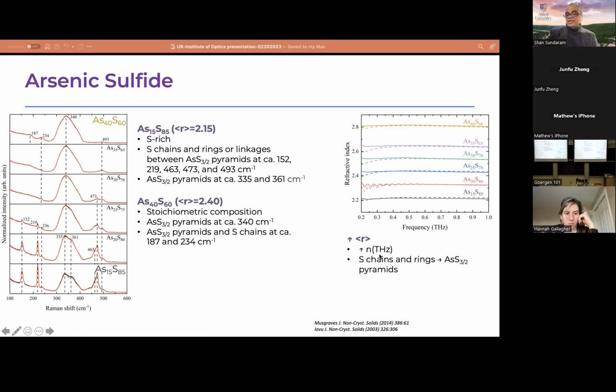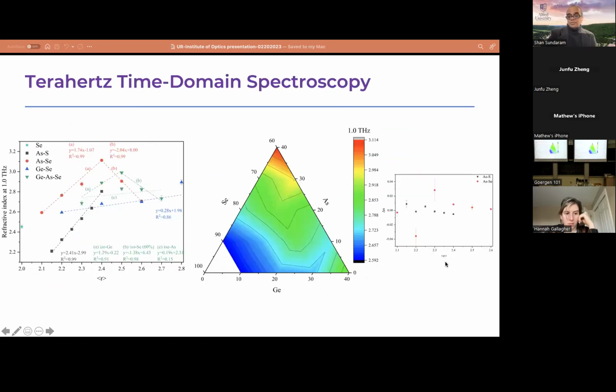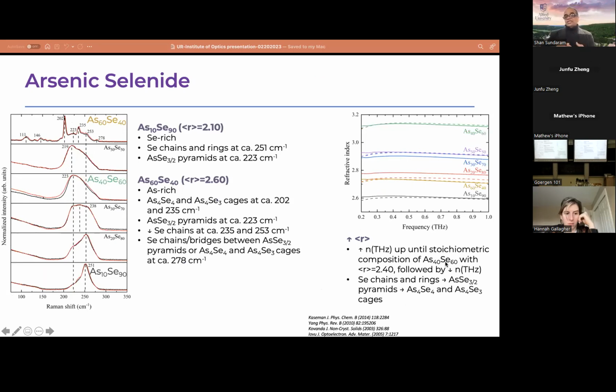So you can clearly see that as the coordination number changes, the terahertz refractive index also increases with the coordination number. So that gives you clearly the idea that by varying glass composition, we can not only play around with the coordination numbers and structural units, I can actually get a range of terahertz properties out of these glass families. So if you look deeper inside, we'll be able to look at the cages and chains, all the structures, which we can recognize using vibration spectroscopy.